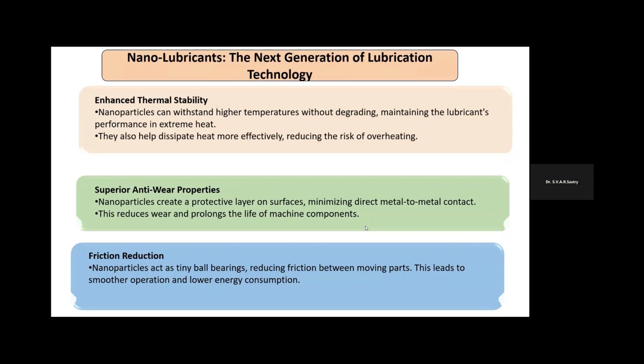So to overcome these limitations and challenges, we can have nanolubricants, which are the next generation of lubrication technology. We can have enhanced thermal stability because nanoparticles present in the lubricants can withstand higher temperatures without degrading, maintaining the lubricant's performance in extreme heat. They can also dissipate the heat more effectively, reducing the risk of overheating in the engine. Then they also have superior anti-wear properties because they can create a protective layer on the surface, minimizing direct metal-to-metal contact, which reduces the wear and prolongs the life of the machine parts.